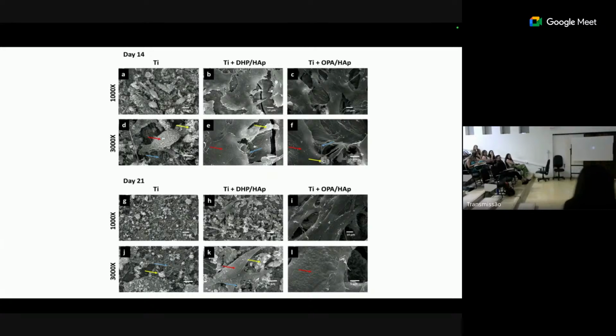But what we found was not that. Even with reduced cell viability, but higher than 80%, the cells mineralized better on the DHP surface. So what I said to the students in the morning, okay, I got a surface with a very high cell viability, it doesn't mean that the surface will mineralize better.